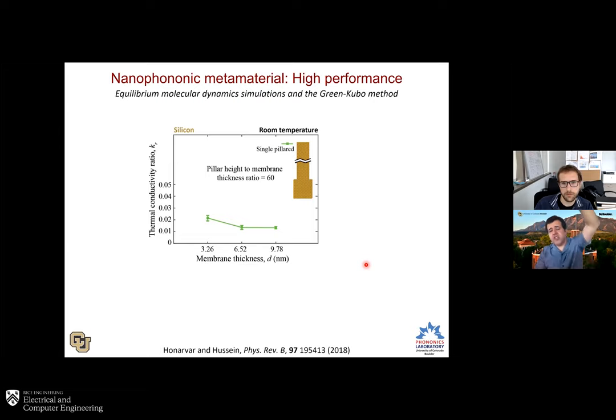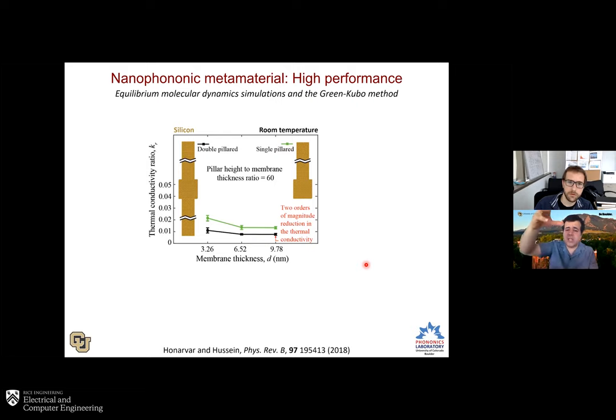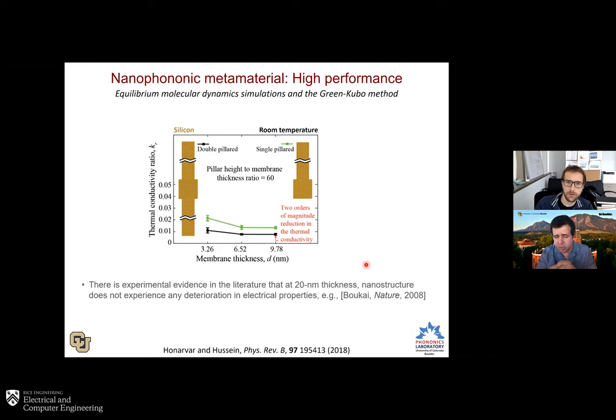If we were to engage a very tall pillar on the order of aspect ratio of 60, we get very strong thermal conductivity reduction. Compared to a pure membrane, we get roughly 50 times reduction. And if we were to add pillars on both sides, we actually found that we can get two orders of magnitude reduction. So this is a very significant reduction in the thermal conductivity.